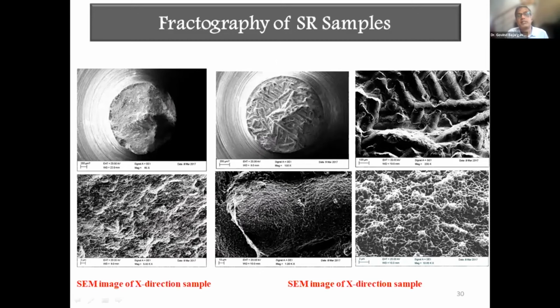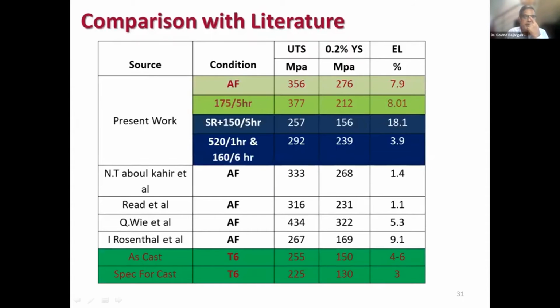And when we test it in the Z sample, we'll always see a failure along this HAZ zone. So to take care of this, we have to have a proper post-processing plan. That is, heat treatment has to be properly done, and we have to select a proper heat treatment cycle. So here are some properties I am showing you, where stress relieving is done, we get elongation of the order of 18%, which is never thought of in aluminum silicon cast alloys.